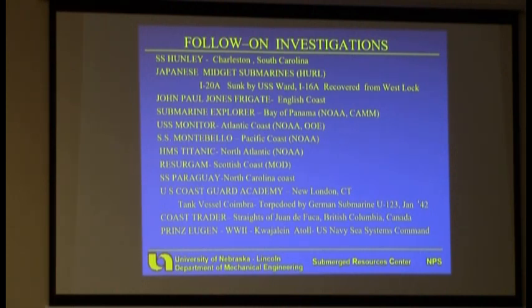at the time we did our analysis, one of the divers, I think it was Dr. Dave Conlon, went over to England and took out a sample of the metal that they used to sheet over the wood to protect against worm infestation. Well, they did the analysis, we did the analysis, and found out that it was brass. It was an alloy of copper and zinc, whereas that had not been developed during the John Paul Jones time period.